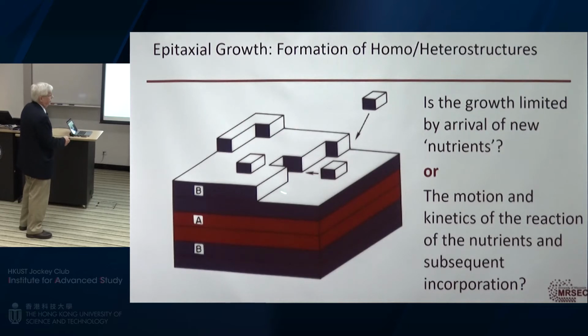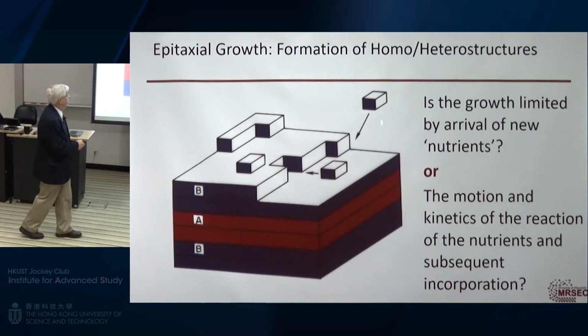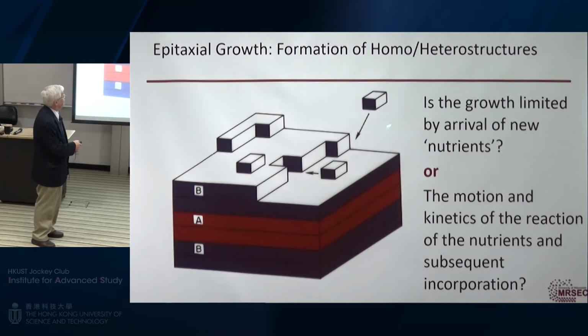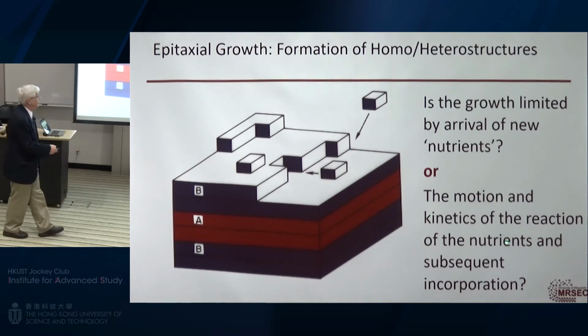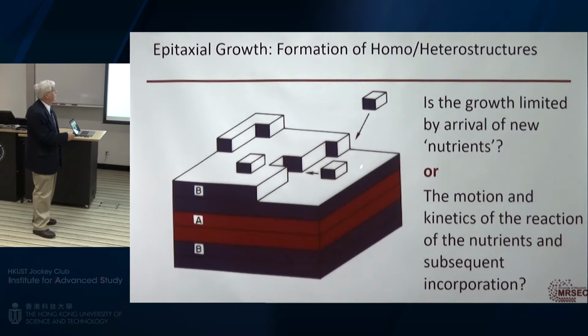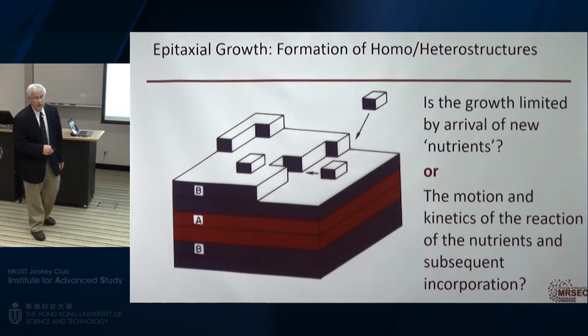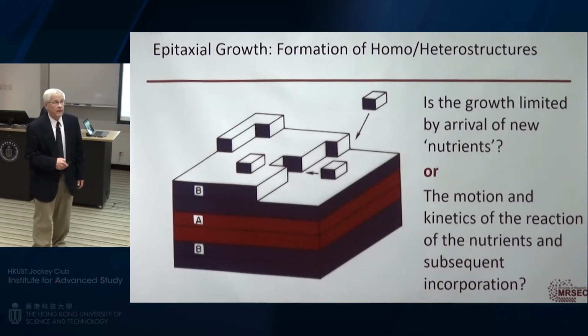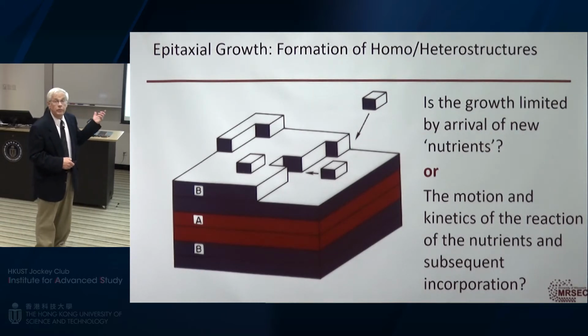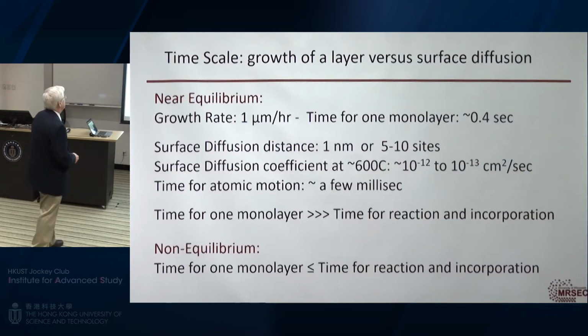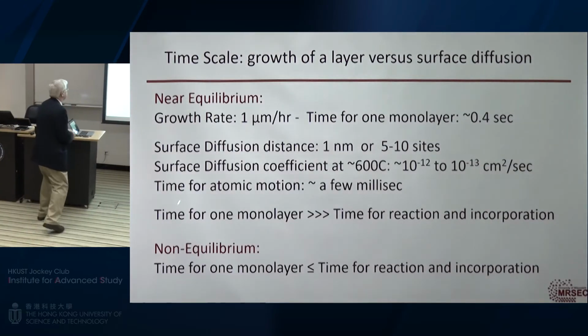atoms come down from the vapor somehow, either as a chemical form or as an element. And so you have to say, what limits the growth? Is the growth limited by the arrival of these new atoms, or by the motion and kinetics of reaction of these nutrients, if it's a chemical, and its incorporation? So what's happening at this growth front will determine what kind of material you'll make. If it's very close to equilibrium, you'll be constrained to thermodynamic equilibrium compositions. So what kind of time scales? How do we look at that?